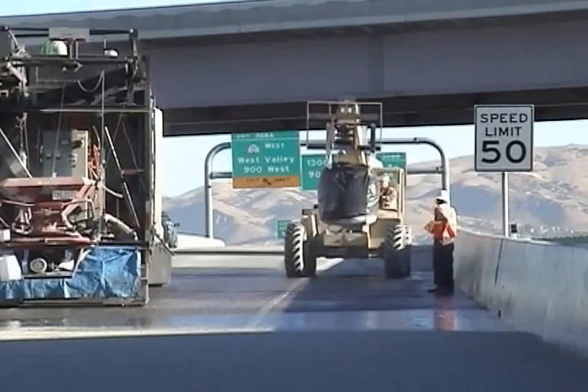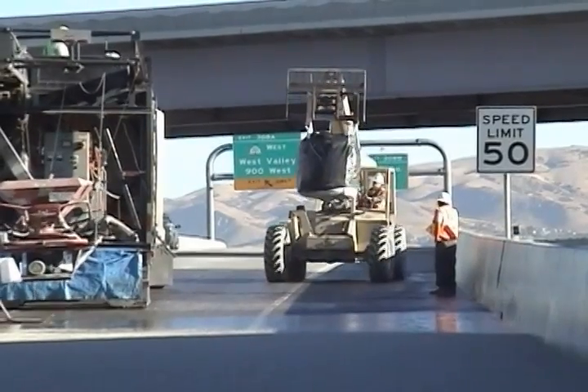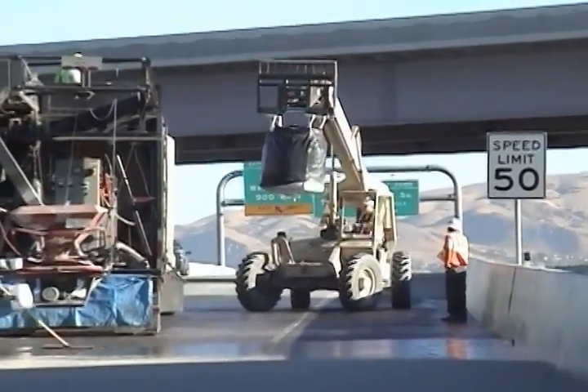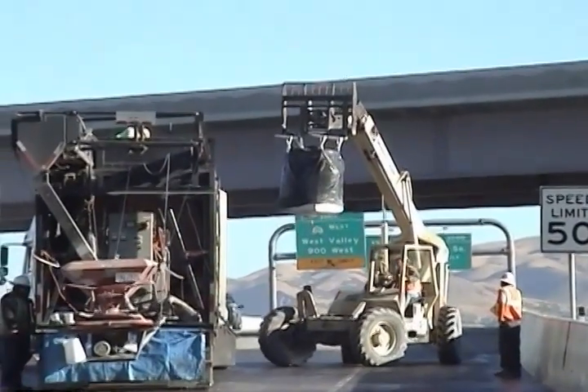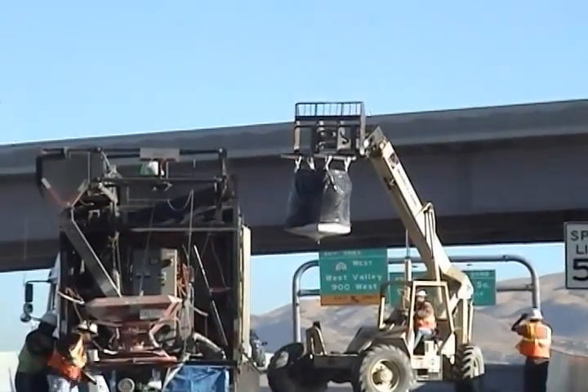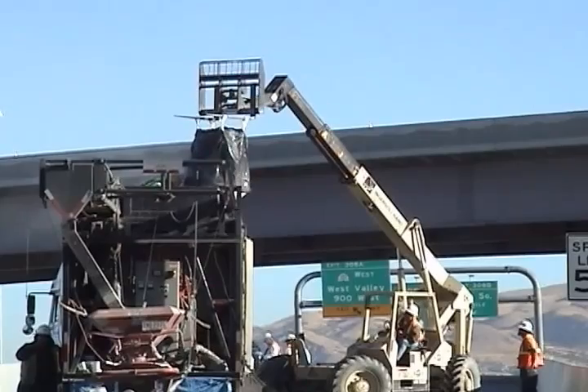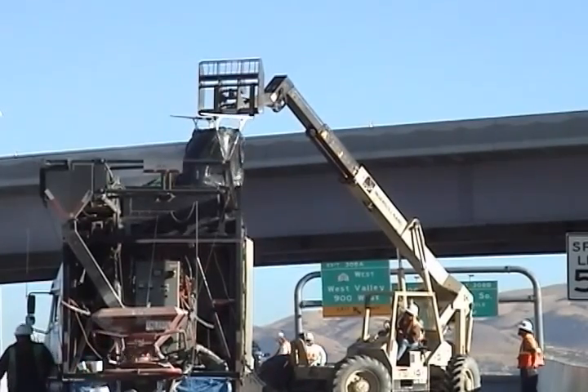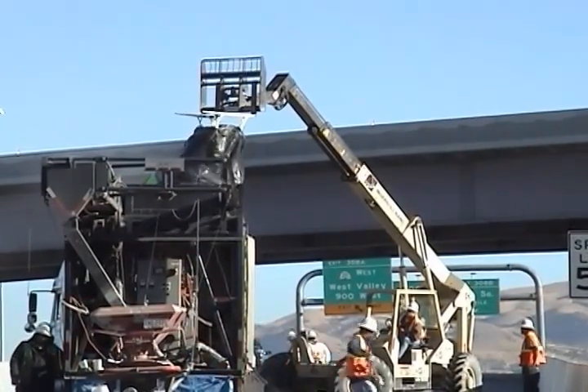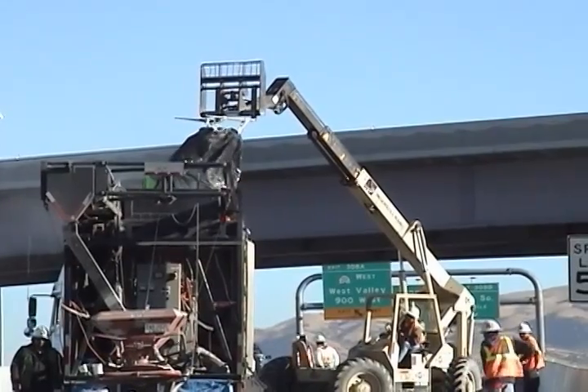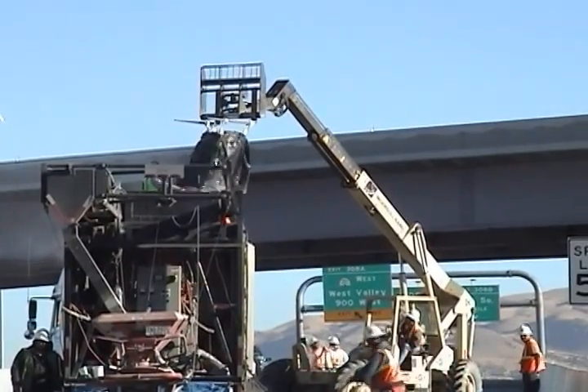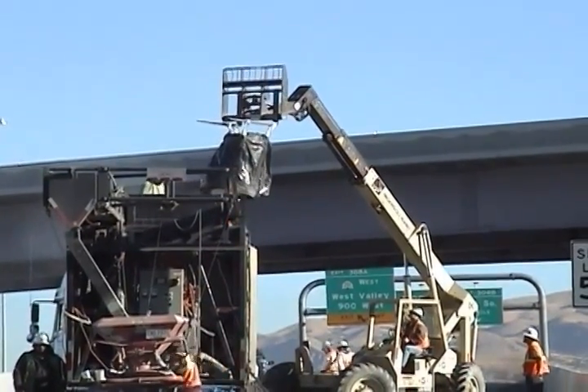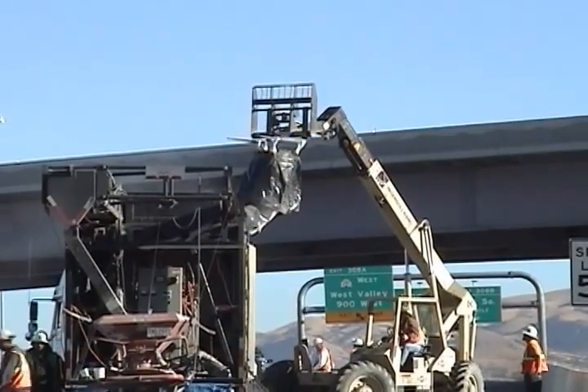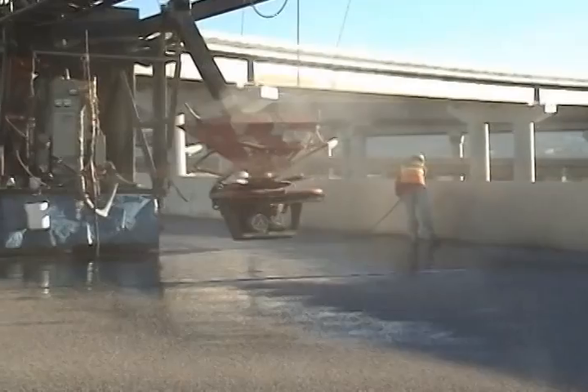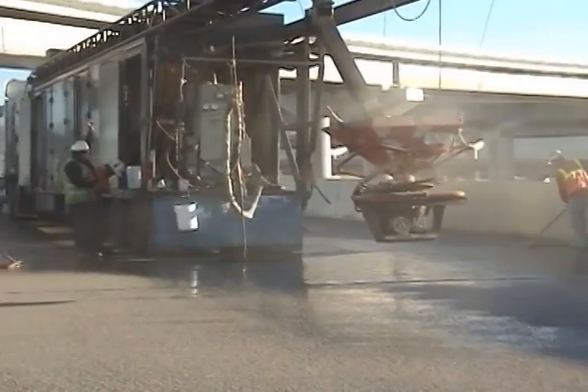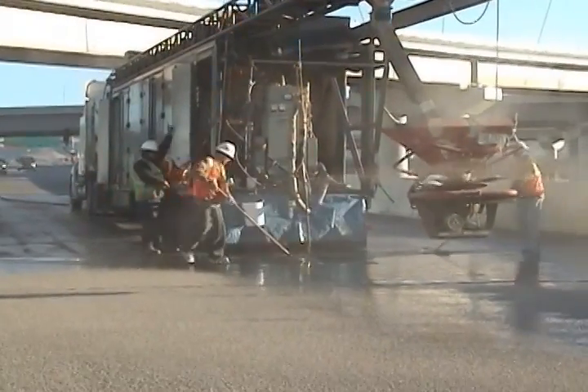Another benefit of using a trailer to carry materials is that reloading the trailer with aggregate is a fairly quick process. The aggregate is loaded into the trailer using a large forklift. Using the Polycarb wagon, 100,000 square feet of overlay can be applied to the deck, cure, and be open to traffic in less than 48 hours and can be expected to last in the neighborhood of 15 years with minimal maintenance. Mr. Wells also explained that in his experience, other overlay systems involving a waterproofing rubberized membrane under a layer of asphalt can be expected to fail after 2 to 3 years of use.